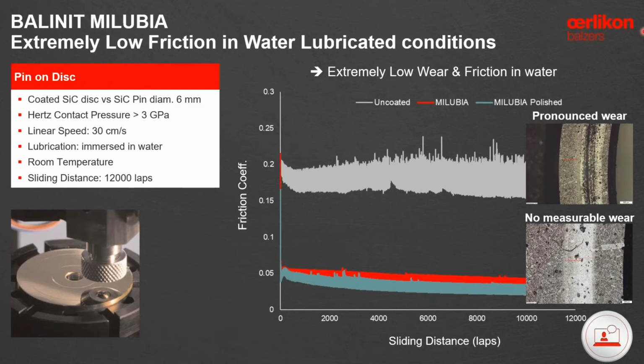In this example, you can see the test parameters on the left, and the lubrication is that the samples are immersed in water. And we'll show you a couple of applications here in a second. So on the right, you can see the profile, the friction of these uncoated discs and pins. And then you can see with MILUBIA and MILUBIA with post-polishing, an even better result in coefficient of friction.